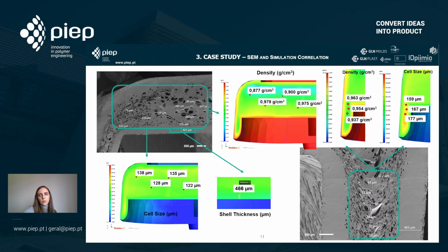Analyzing this and comparing the results with a numerical simulation, we focused on the cell size of the part, the shell thickness, to evaluate if the simulation could in fact evaluate the shell thickness, and the density. In this case, the cell density is not as visual, and the results that we obtain are very uniform.